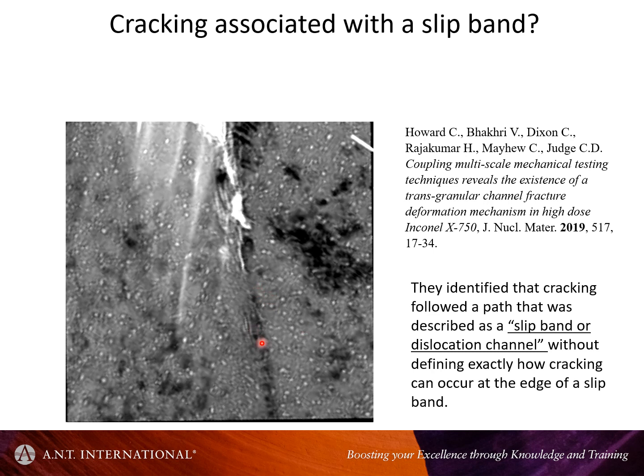I mean, if this was a slip band in the classical sense of a slice through a slip plane, there are two things. A, it wouldn't show this contrast, you wouldn't see any contrast change. I mean, this looks like there's a different tilt here. And B, the edges of a slip plane are artificial.